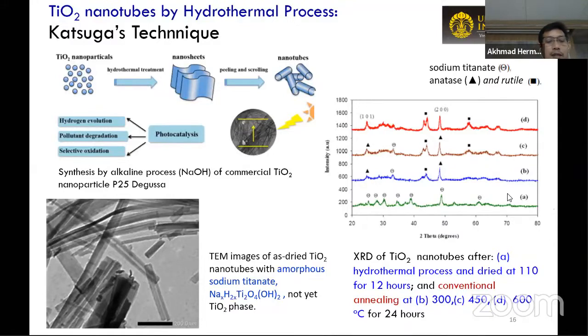That's why, based on the TEM image, we can see that there is no indication that it is a crystalline material. What should we do? We have to enhance the crystallinity of TiO2 and get rid of the sodium element from the nanotube by using the conventional annealing process. Yeah, this is the X-ray diffraction result.